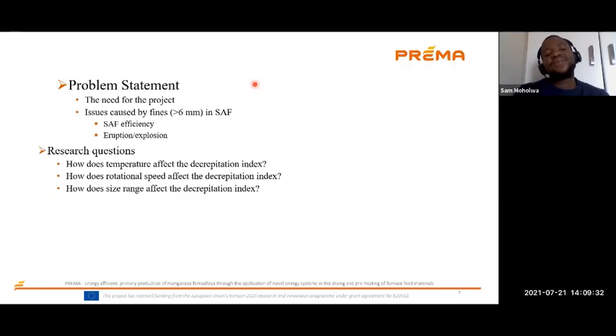But if you are feeding fines, that bed of minerals won't be gas permeable. In other words, the gas will not be able to escape properly through the bed, and we may not have a sufficient pre-reduction, meaning that we'll use more coke than we're supposed to. And the other thing, if the bed is blocked enough, these gases that are being produced at the bottom will accumulate and accumulate. Eventually, we'll have an explosion that is a safety hazard.